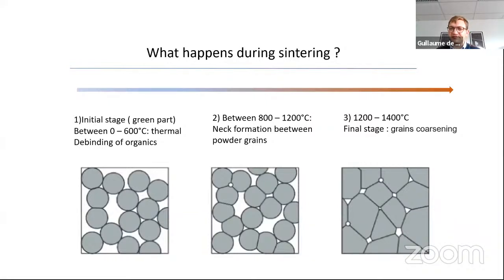What happens during sintering is, basically, you'll have three stages. The first one is the thermal debinding. We talked about it already. Then between 800 degrees Celsius and 1000, 1200, you're going to start having some connections between the grains, which will make the part solid. It will give some strength to the part. It's not yet a dense metal, but it's relatively strong.